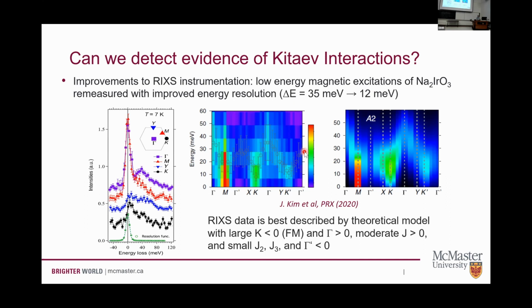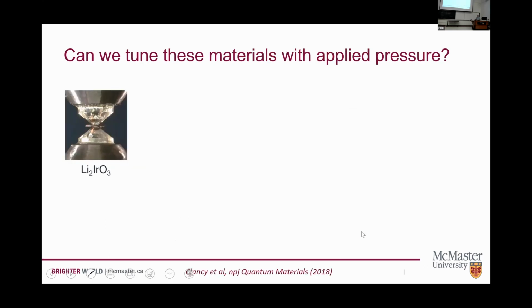And you can compare this to those theoretical models again. And instead of just saying, is there a Kitaev term or not, you can actually try and put constraints on the size of these, whether they're ferromagnetic or antiferromagnetic. And so what we see here seems to be consistent with a ferromagnetic Kitaev term that is fairly large compared to these other interactions. Okay, so again, a good sign that we have something that looks Kitaev-like.